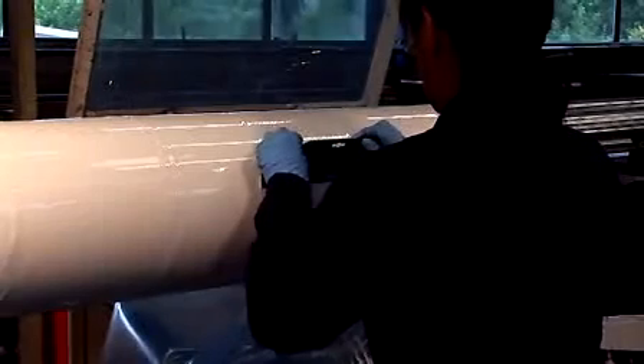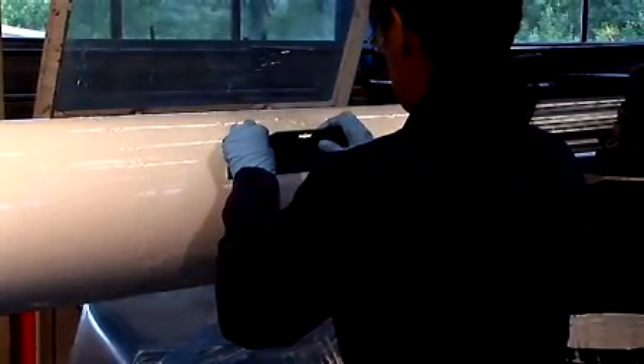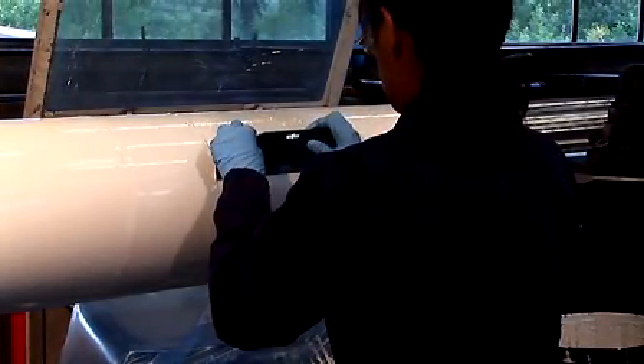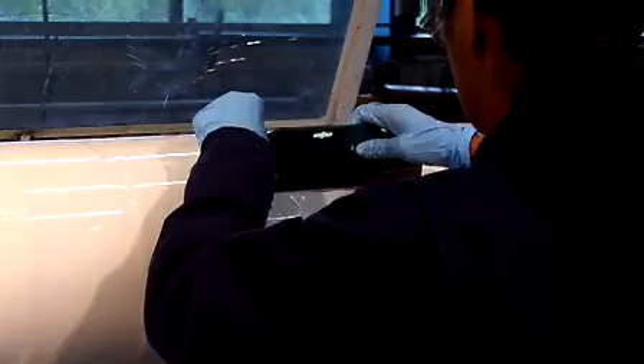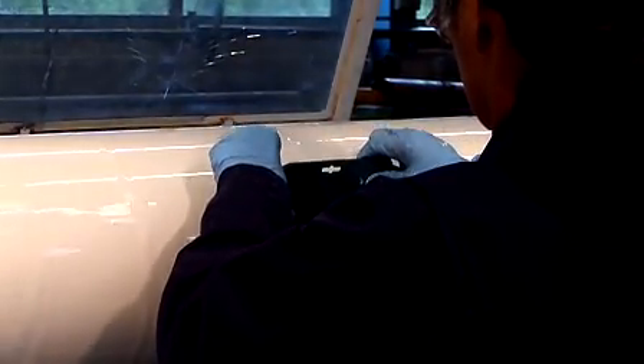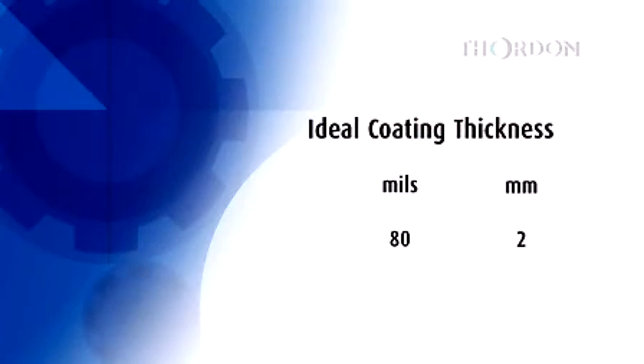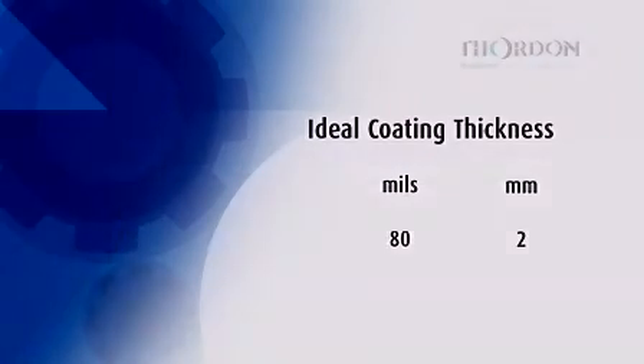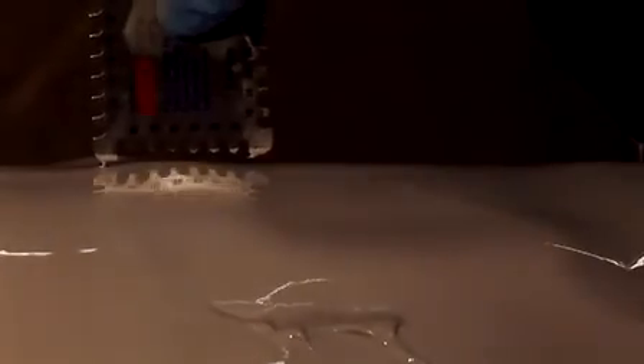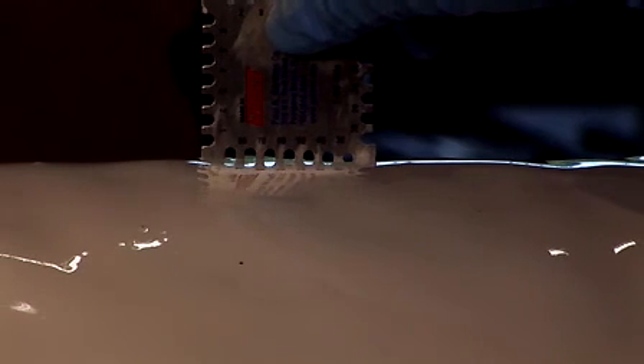60 feet per minute. Once the first kit is applied, hold the trowel obliquely to smooth the surface of the coating and repeat along the shaft, taking care not to remove too much coating material. Thor Coat should be evenly applied at a thickness of 2 millimeters or 80 thousandths of an inch, measured by the wet coating thickness gauge supplied with the kit. Holding the gauge at a 90-degree angle to the shaft, press it firmly into the film, withdraw, and note the deepest tooth with coating and the next highest tooth without coating. The teeth are marked in mils.